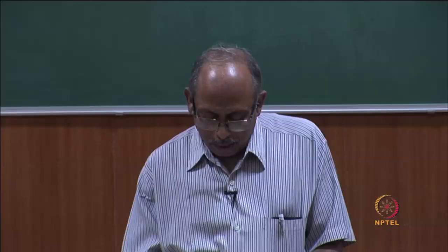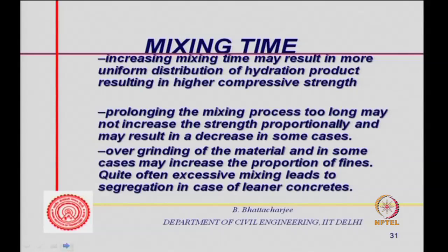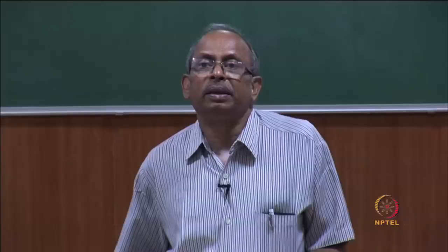If you go on increasing this, it may not increase the strength proportionally, and sometimes it can even cause a decrease. There is a limit up to which you can do it, because mixing may cause over-grinding of the material, too much abrasion between aggregates, and in some cases may increase the proportion of fines if the aggregates are weak.